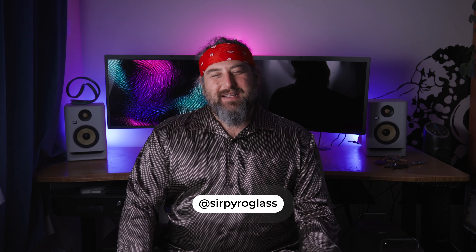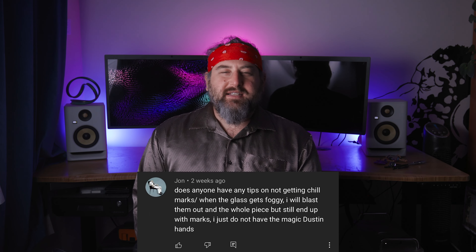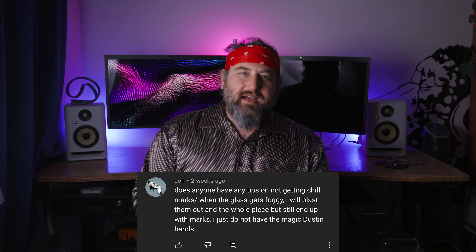Hey guys, welcome back. Thank you so much for joining us for this collaboration — it was an honor and so much fun having Pyro here. Check out his work, SirPyroGlass on Instagram, and make sure you check out part two. I've got some questions you guys have asked. John is asking why sometimes when he's working, the glass gets foggy and seems a little rough on the surface. There are kind of two answers to that. Most likely what's happening is you're moving the glass while the core is a little hotter than the skin. What could be happening is called devitrification — that's when the glass molecular structure changes from an amorphous solid to a crystalline structure. A way to resolve this is to make sure that when you're moving the glass, it's nice and hot — make sure everything is hot, you're not twisting it, and that'll help you keep your glass glossy.